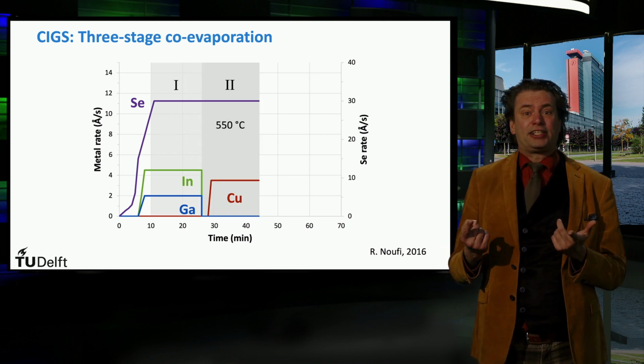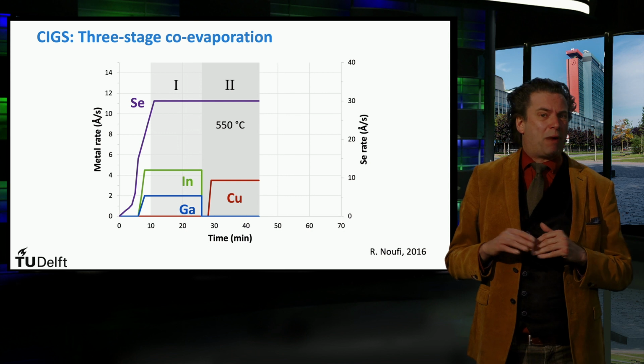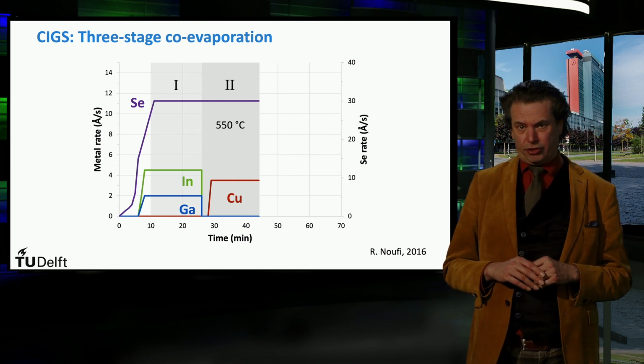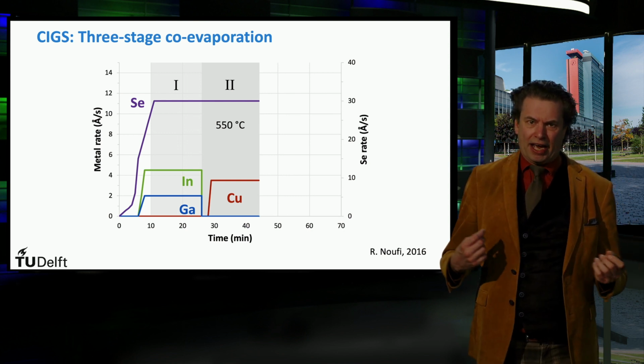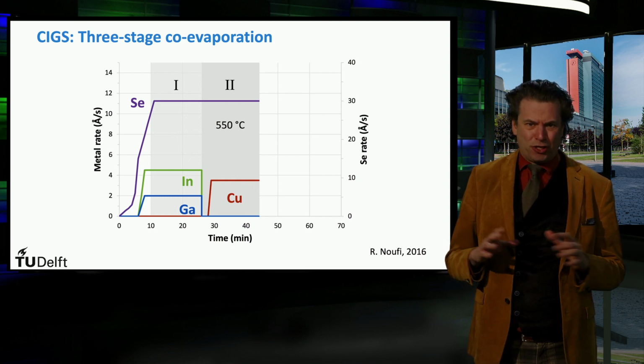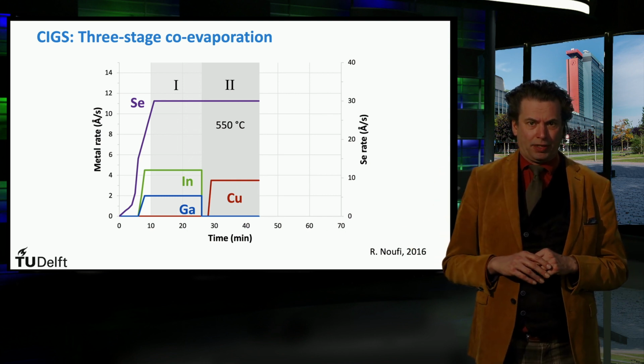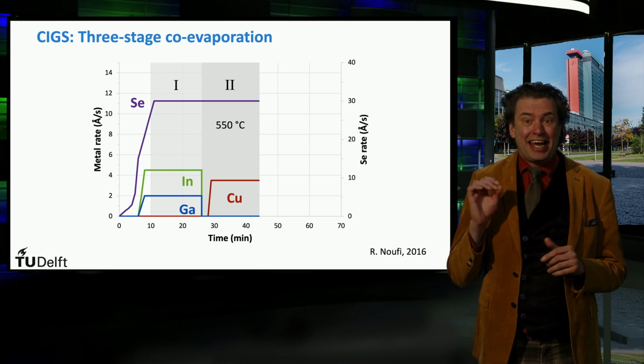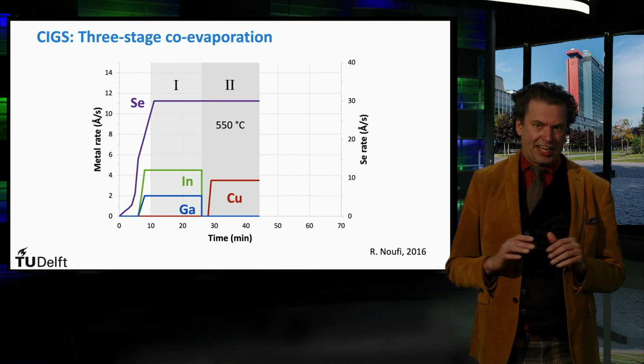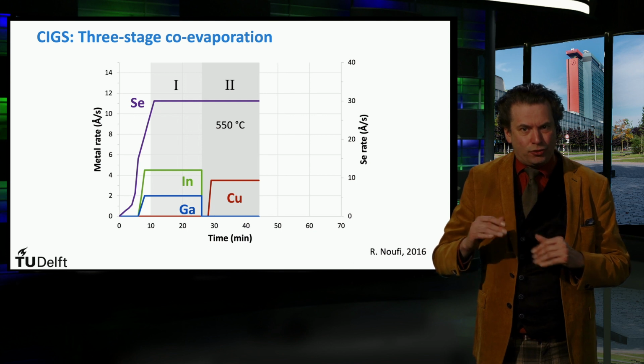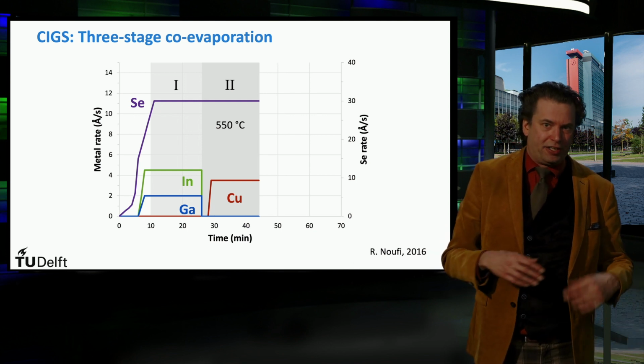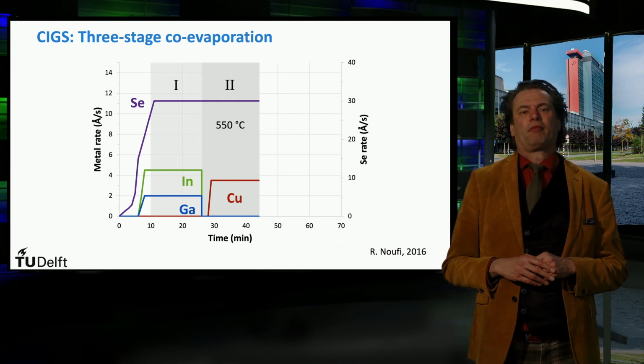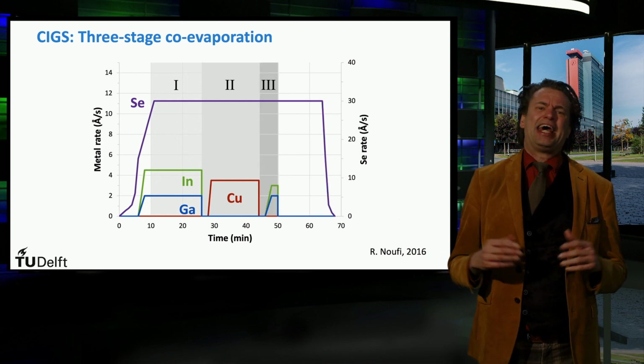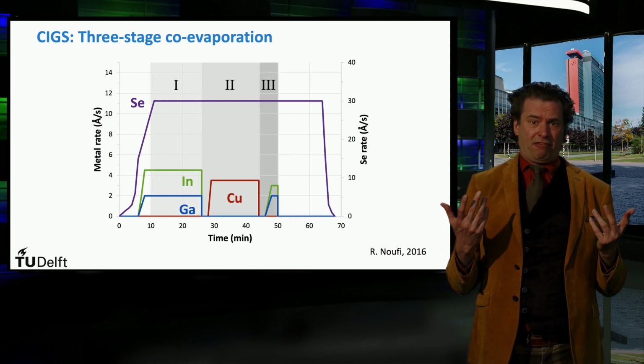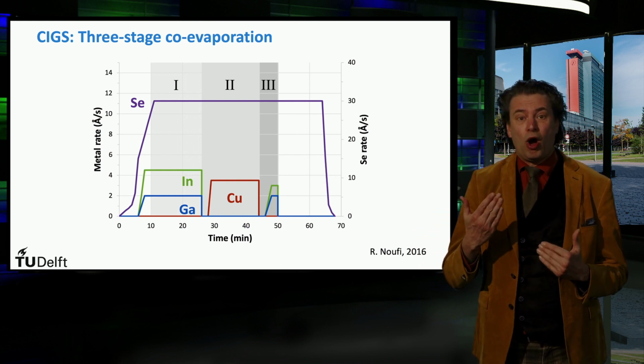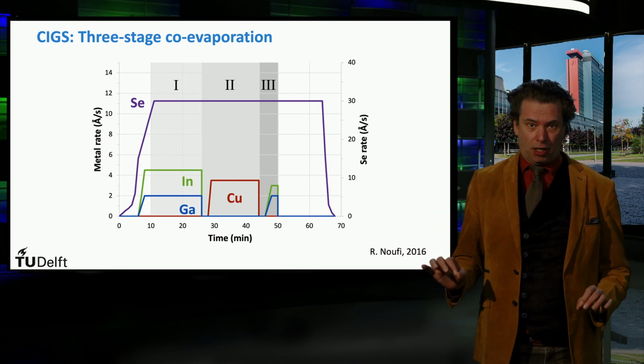In the second stage, the temperature is ramped up to about 550 degrees Celsius, while both the indium and gallium evaporation is stopped and the copper rate is increased. The second stage will initiate crystal growth of CIGS as copper will blend into the porous first layer of indium, gallium and selenium. In the third stage, again, a layer of indium and gallium is evaporated in the required ratio while the copper evaporation is stopped.